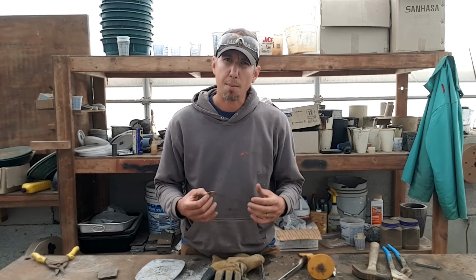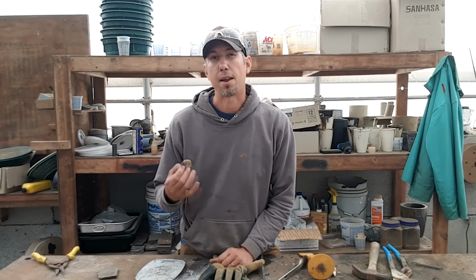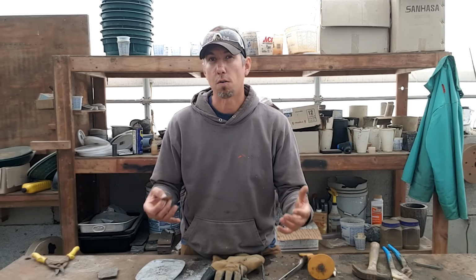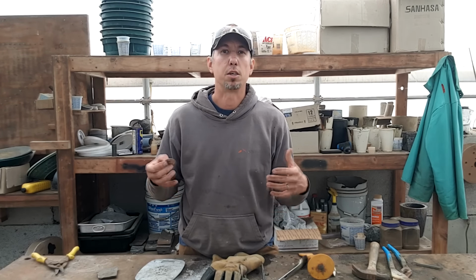But I'm really happy with the ability of scorifying a bunch of base metal collector metal, and then oxidizing it away so you don't have to cupel a kilogram worth of lead. You can oxidize it away and then have a much smaller bead that you've got to deal with. So that works out really good. And in addition to that, that tells me that I can take a kilogram of lead and use it over and over again as a base metal collector, maybe 5-10 smelts, continually enriching it. Then at the end of that, when you're ready to recover your precious metals, you can oxidize away all that lead by scorifying it, putting in oxidizer, and then recovering your precious metals.